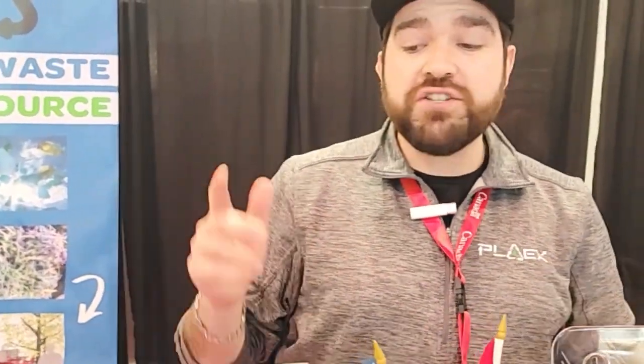Let's talk about the plastics. Is this like polypropylene, polyethylene? What's the composite? We are able to take a wide range — types one, two, four, five, six, and seven — so that incorporates most of your polymers. We can't take PVC and we can't take things that incorporate cellulose. That is due to the fact that our system puts heat towards these products in order to make that composite.